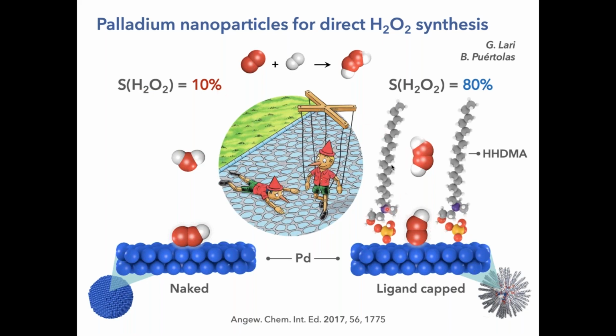And in contrast, when the ligand is covalently bonded to the palladium surface, the selectivity to hydrogen peroxide increases to 80%. And this is due to the fact that the steric interactions between this ligand and the density of the ligand on the surface of the nanoparticle made that some of the intermediates, instead of lying horizontal on the surface, lie vertically. And the vertical orientation of the OOH intermediate in hydrogen peroxide synthesis leads to high selectivity to hydrogen peroxide because the oxygen-oxygen bond leading to water, the undesired product, is not cleaved.